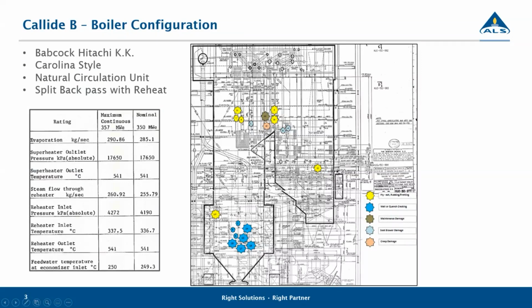The boiler's main damage mechanisms are largely fly ash erosion, soot blower erosion, and water wall quench cracking. But then this particular failure popped up a couple of times for them as well. Steam conditions are 541 for both the main steam and reheat, and it's a 350 megawatt unit.